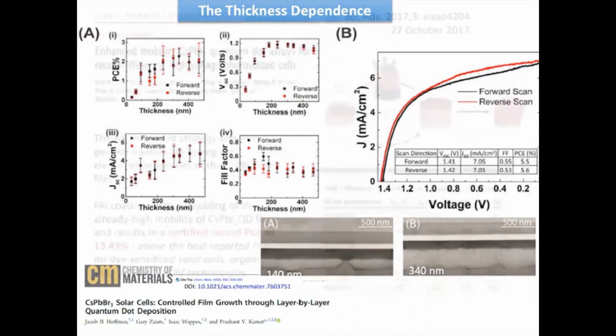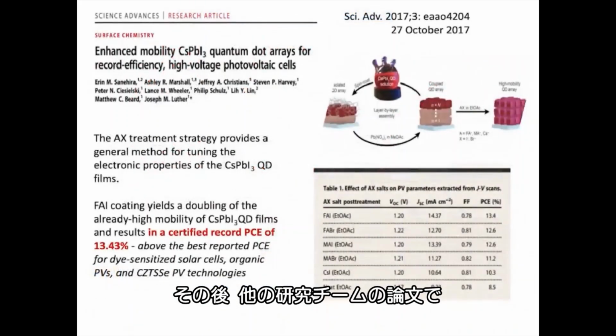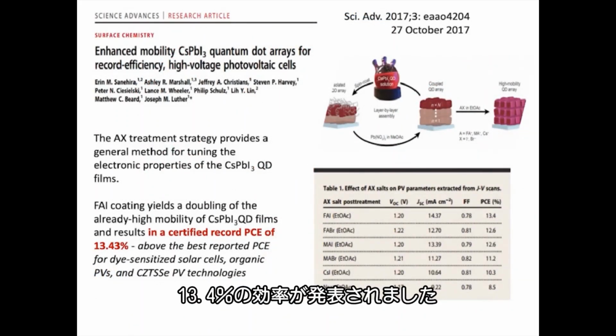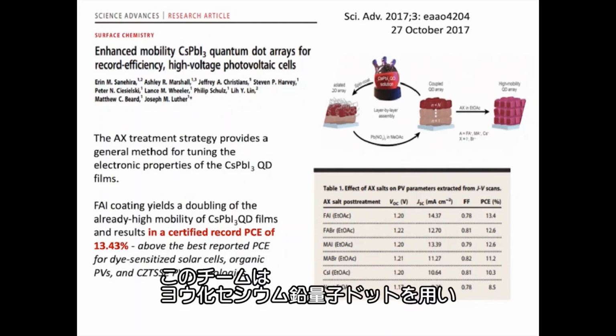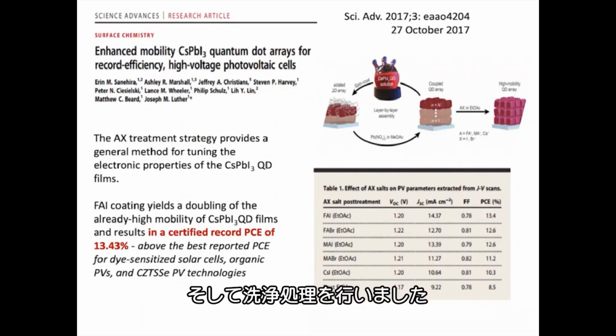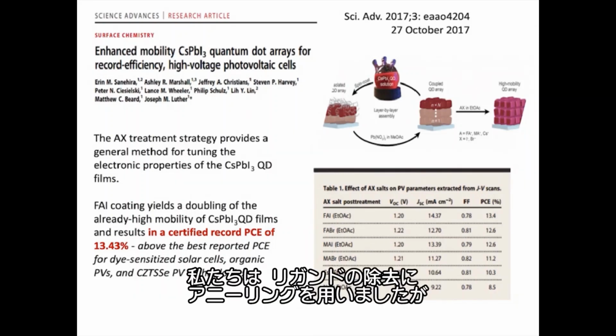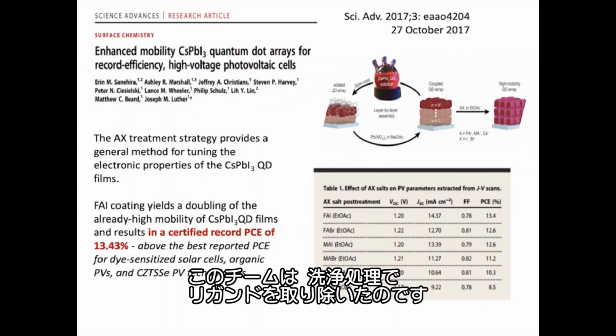Soon later, a paper from the NREL group came out with an efficiency of 13.4%. They used cesium lead iodide quantum dots and a washing technique. In our technique, we anneal to remove ligands. In this case, they washed to get rid of the ligands.